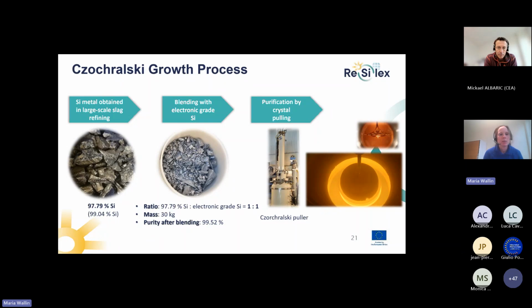And here we use material from the large scale trial, and it was, as I said, 97.79% pure. Because it's quite dirty as a starting material, to ensure that we could tolerate it, we blended it in with high purity silicon, electronic grade, 50-50, and the total mass was then 30 kilos. After we blended these 2 streams, we had a starting purity of 99.52%. And here you can see the pulling again, and it's turning, it's lifting out.